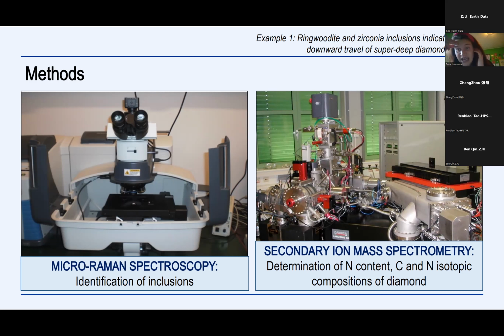Nitrogen is the main chemical impurity that we can have in the crystalline structure of the diamond, and its presence is very important to have information about the diamond formation. Through this analytical technique, we also determined the carbon and nitrogen isotopic composition of our diamond. This determination is also very important because it allows us to understand the possible carbon and nitrogen source of the diamond that we are studying.